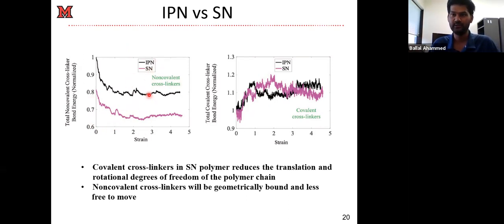But in case of IPN, in one polymer chain you have only covalent crosslinkers. In another polymer chain you have only non-covalent crosslinkers. So this restriction is not there for the IPN, which creates a more favorable situation for the non-covalent crosslinkers to crosslink. And these non-covalent crosslinkers are what is contributing to the better mechanical properties of this IPN in comparison to the SN. So that's what is happening.